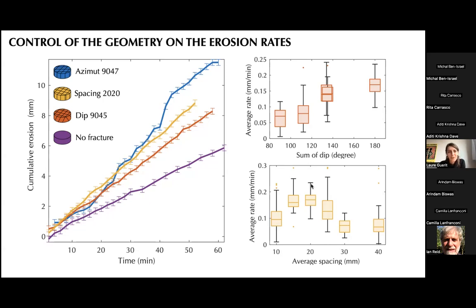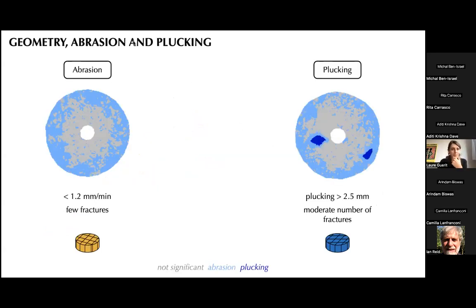So this was the erosion rate, and if we merge erosion and processes, we know we have experiments dominated by abrasion that are associated with low erosion rate. And we observe that all of these experiments are associated with only a few fractures. I cannot show all of that, but please believe me, all these experiments have only a few fractures.